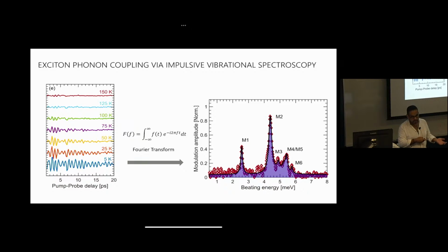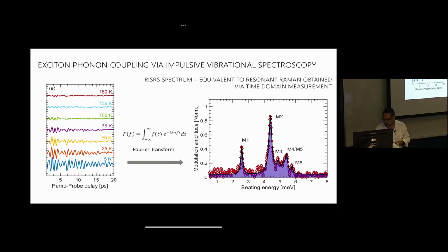If it's a Raman allowed vibration, it will have very high amplitude in the Raman spectrum, whereas this one has much lower amplitude. It's coupled much more weakly to the photocarriers, right? And so you've got your spectrum. It's very clear, very well defined, very sharp peaks.